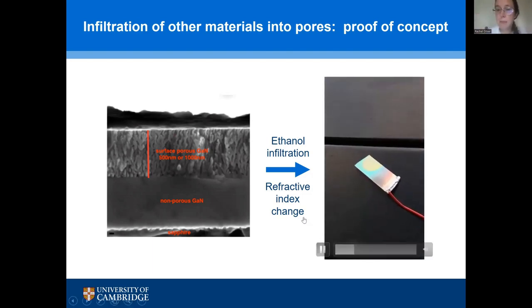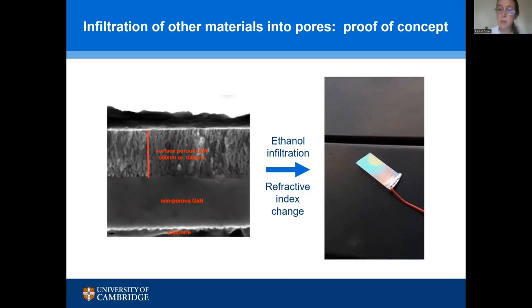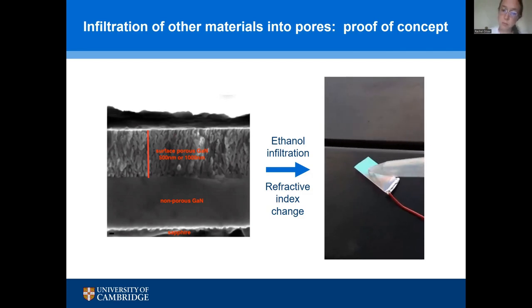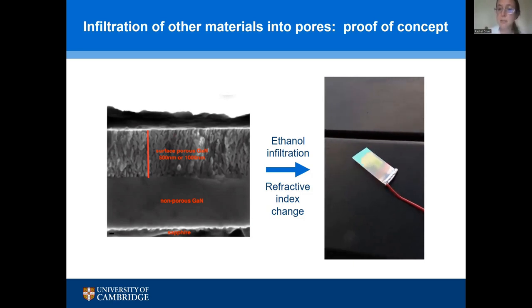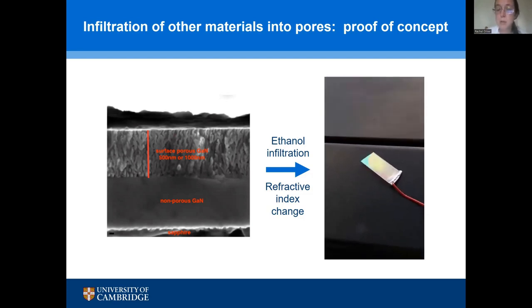And then as it evaporates, you'll see the yellow spot we've got currently shrinking, and we see fringing developing as the refractive index and the volume of ethanol infiltrated into the device changes. And he'll do it once more here. And there we are. We can see the ethanol spreading out and really sinking into the device. And we're almost going to normalize the refractive index to be the same as the surrounding material. And then as the ethanol evaporates, we'll return back to having a different refractive index, which is the refractive index of the porous gallium nitride.